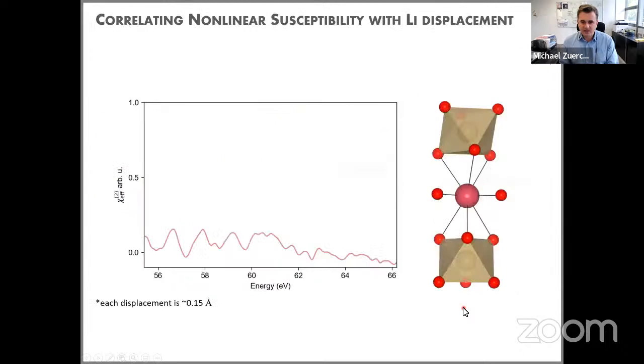So now let's look a little bit at the calculations and then the data. What do we really learn from this? The first thing I want to show is a number of numerical simulations. Our collaborators set out to first ask what the second harmonic spectrum looks like. If we measure the spectrum, how can we infer some quantity, like the amount of lithium displacement, or quantify the geometry in the system? So they did some calculations to see, for different lithium displacements, how much change of the second harmonic spectrum we can expect, and what the shape would roughly look like.